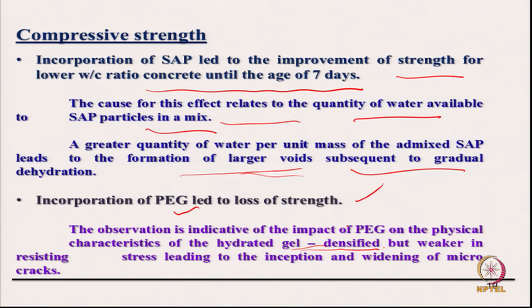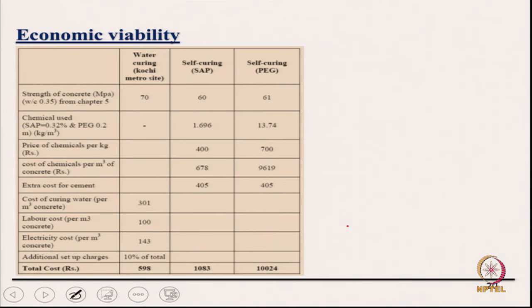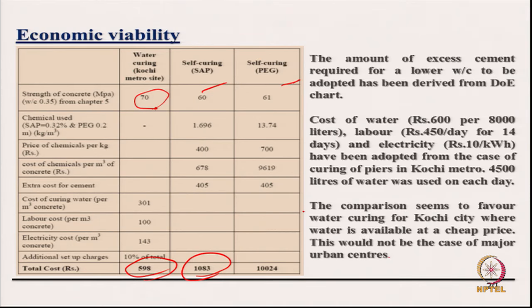For PEG, one can look into the microstructures and things like that, so there is a possibility of using all those. If you see the economics part of it, one can find out the cost, because this itself has some cost implication. The total cost of concrete one can calculate for a similar strength of concrete. If you take a practical concrete used in Kochi Metro with self curing, the cost per meter cube increases significantly. The amount of excess cement required to lower the water cement ratio, if you want to get the same strength, means the cost of cement will also increase.